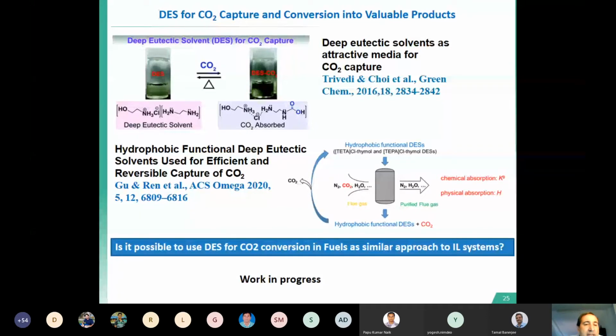In this case, they are using a deep eutectic solvent and a combination of a protonated amine chloride, a salt, and a diamine. In the presence of CO2, this is reversible. It's possible to capture CO2 and to remove CO2 again from the system.